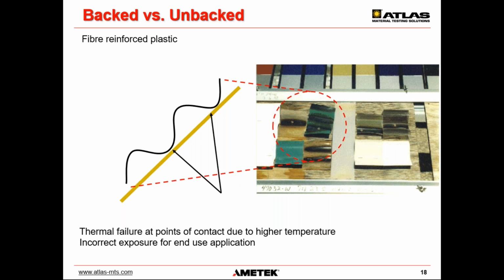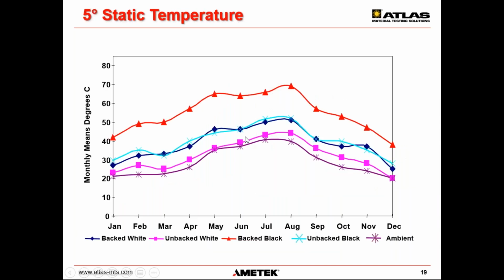So that put his material now in a backed configuration, because now they were backed up against this plywood that you see right here. Well, because of the corrugated nature of these materials, you can see that in these touch points where it was actually backed, you got some pretty severe thermal degradation in these areas right here that likely would have never happened, because here in these unbacked locations, you don't see that same type of degradation. So based on this, it would be pretty clear that the end use of this material was mounted in a condition that did not match the service environment and really was probably considered to be an incorrect exposure.